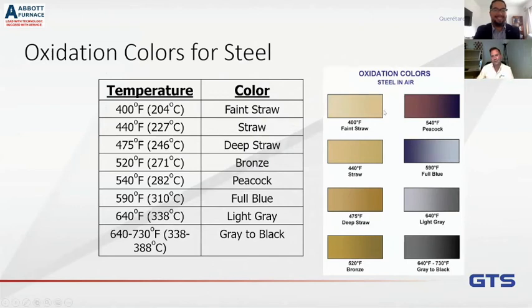Okay, and what this is, steel will oxidize to form different colors at different temperatures. Regardless of it being air or water, it'll form these colors. And so at about 200 degrees C, you have a faint straw, and you can see this range. But as we go up in temperature, you notice that the colors become more brilliant, right? If you're going to ruin a part, let's make it pretty, right? So they become peacock and blue, okay?